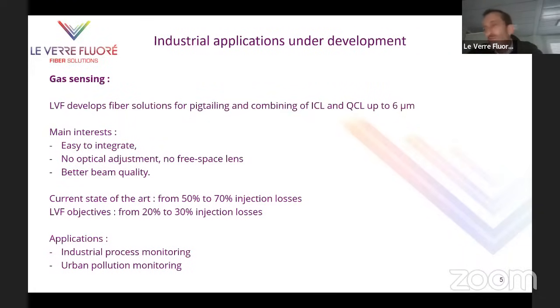Currently, when we try to couple an ICL or QCL through a fiber, we get 30% to 50% transmission, which is 50% to 70% losses. We have developed and integrated a solution where we have a breakthrough in terms of transmission, because we only have 20 to 30% injection losses, which allows us to improve significantly the signal to noise ratio, which is key when you make measurements. The applications are industrial process monitoring and urban pollution monitoring.